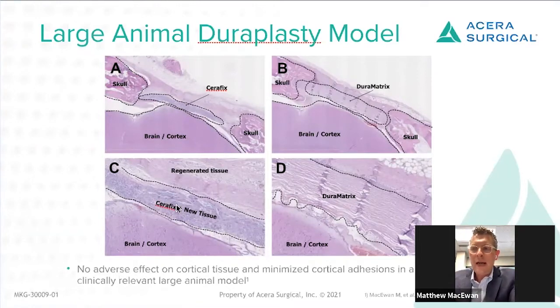What we found was, in this case, at 4 weeks postoperatively, we saw a lot of cellular infiltration into our electrospun matrices. We saw very little adhesions to the underlying cortex, very little inflammation compared to the Duramatrix material or the collagen material here on the right, which was so dense and so highly cross-linked that cells weren't even able to penetrate it. And so I think it really provides an interesting point in that how these electrospun matrices actually can promote and incorporate cells into the matrix very quickly and start to set up that new tissue that's needed to repair these types of, in this case, dural defects.